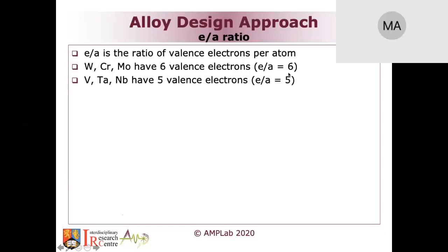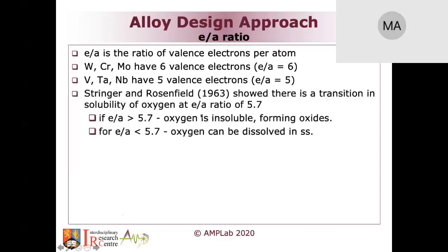Now, a very important paper by Stringer and Rosenfield from 1963 said that there is actually a transition in the solubility of oxygen in materials, and that happens at an E/A ratio of 5.7. If the E/A ratio of the alloy that you're processing is greater than 5.7, oxygen is insoluble and it will form oxides. Whereas if it's less than 5.7, oxygen can be dissolved in solid solution.